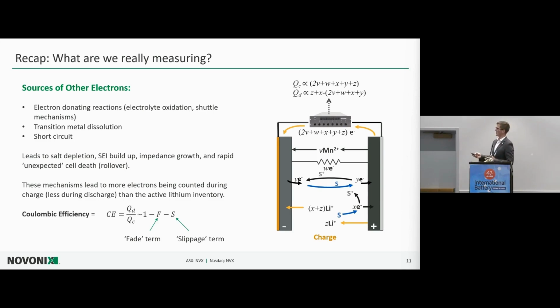So other sources of electrons are all kinds of other electron donating reactions or mechanisms. This can be electrolyte oxidation, shuttle mechanisms. So I just walked through a few of them here. When we have something like manganese dissolution happen from our cathode, in order to create charge balance in our cell while we're charging, we're also going to send a couple electrons through this external circuit and count those. If we have a short circuit, small self-discharge within our cell, we just create this electron shuttle around, and we can be counting that. We can have reversible redox reactions.